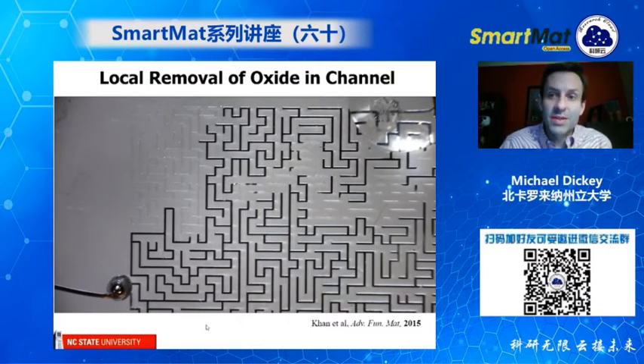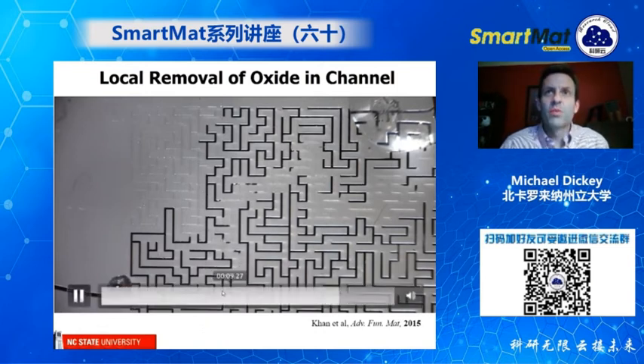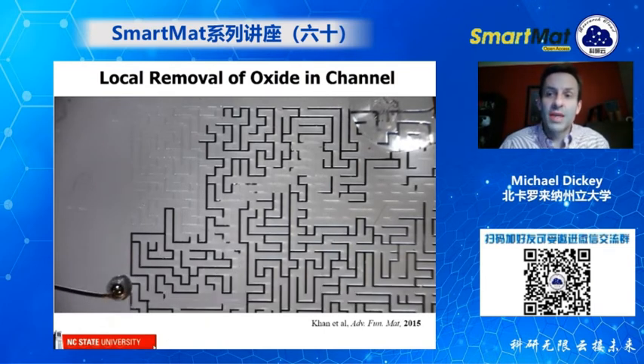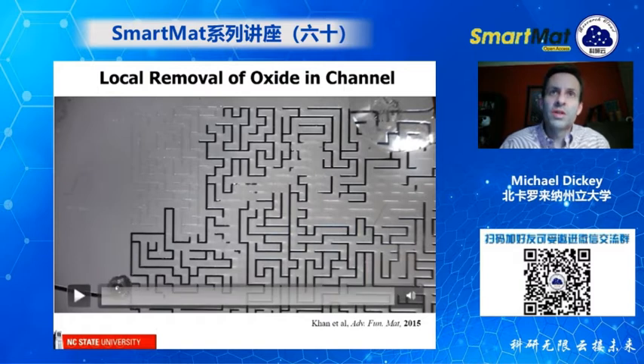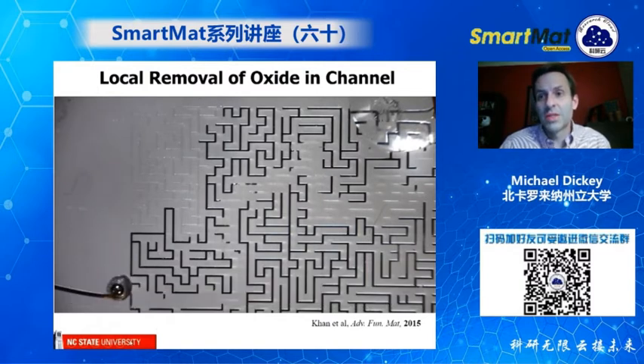So this allows us to selectively remove the liquid metal from these microchannels because, again, we are simply removing the oxide layer from this leading edge, and the metal is trying to bead up here to minimize its energy. So this is really cool because you can actually solve a maze using liquid metal.